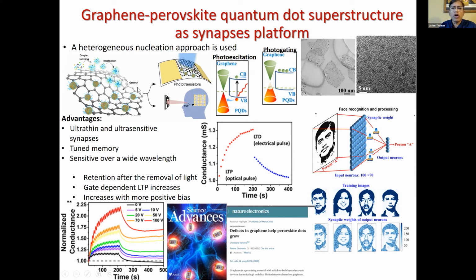As you know, these quantum dots, especially the perovskite quantum dots we use in this case, can absorb a lot of light and convert it into charges. By tuning the energy levels here, there can be a photo gating effect, and you can give the memory effect to this film. That's the advantage of tuning the energy levels of the materials you attach onto the graphene. So you can have tuned memory, short-term memory as well as long-term memory, like our brain.